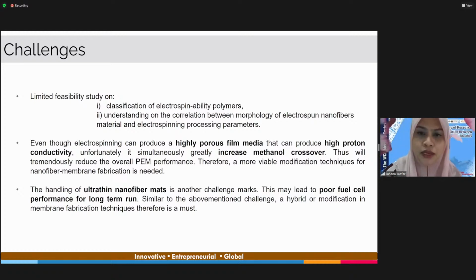Even though electrospinning can produce a highly porous film media that can give high proton conductivity, of course, without having any polymer matrix in the membrane, for example, if we only have the nanofiber alone in the film media or mat, the proton conductivity will be high. Unfortunately, it will simultaneously increase methanol crossover, so this will tremendously reduce the overall PEM performance. Therefore, more viable modification techniques for nanofiber membrane fabrication are needed. One of them is what we have done and I have reported just now.